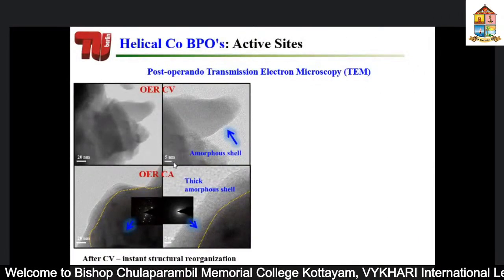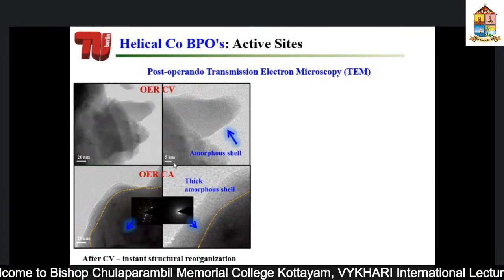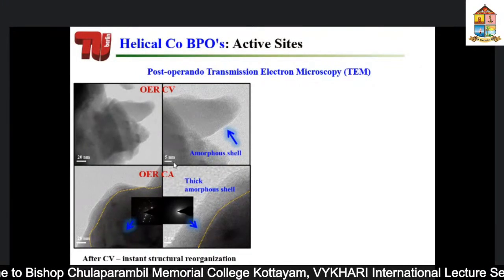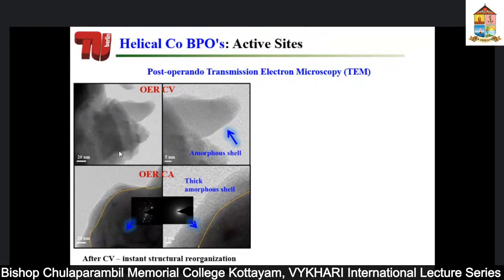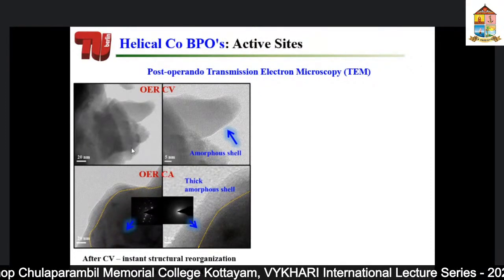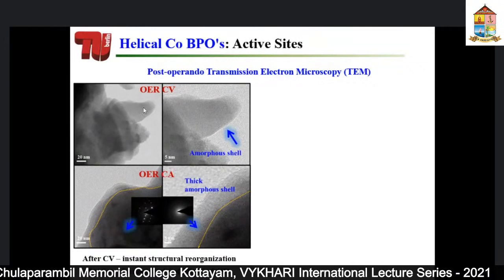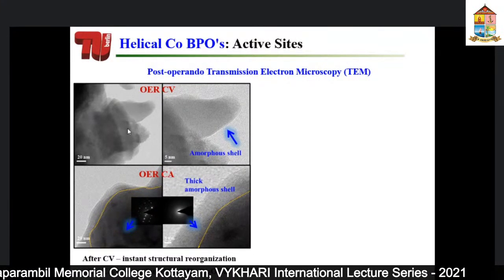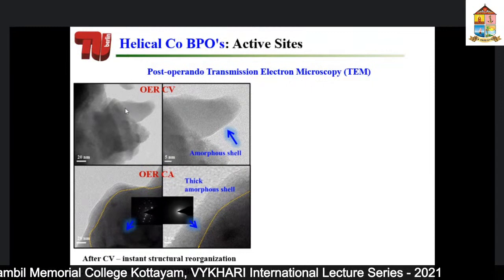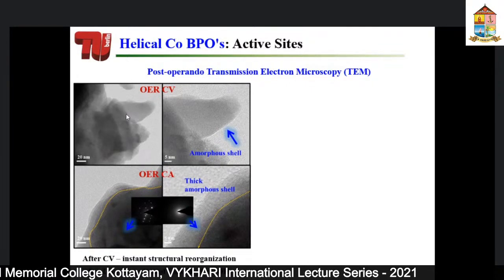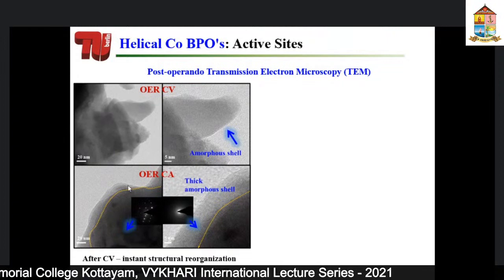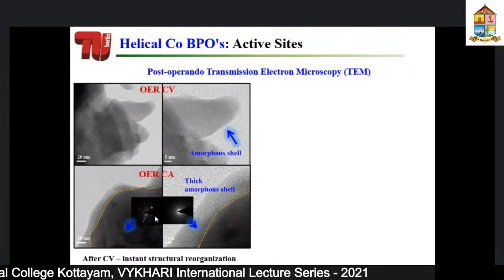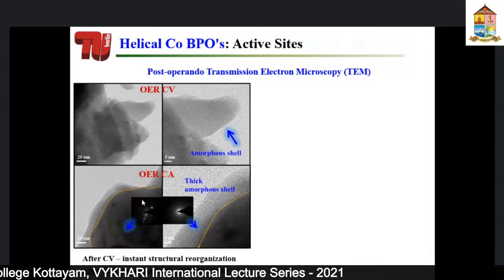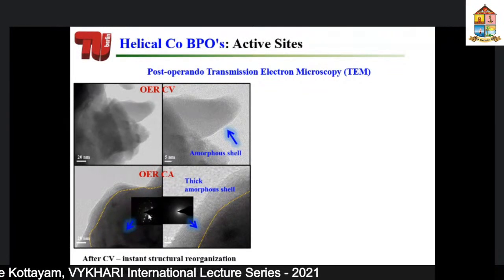In the beginning, I told you that it's important to know if the catalyst remains, or if it is a real catalyst for that matter. So we tried to look at different microscopy or different analytics. One of the pictures I'm showing you here is from transmission electron microscopy. This is after a very short time exposure to oxygen evolution reaction, and this is after a long time. And what you could see here is the reflection obtained from electron diffraction. This says that the material is crystalline,